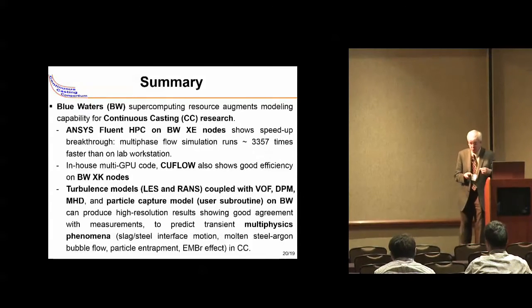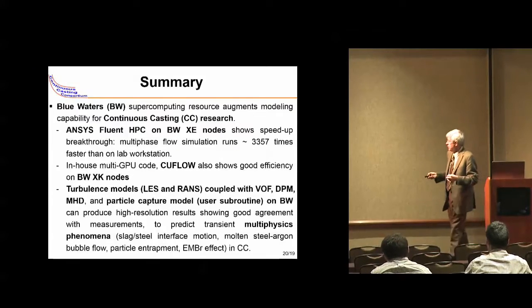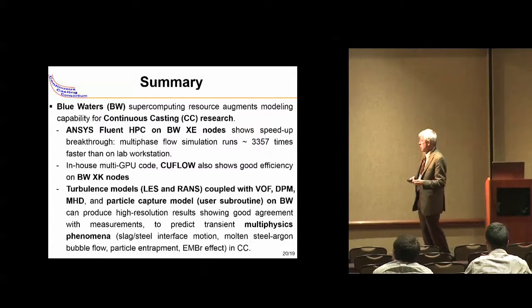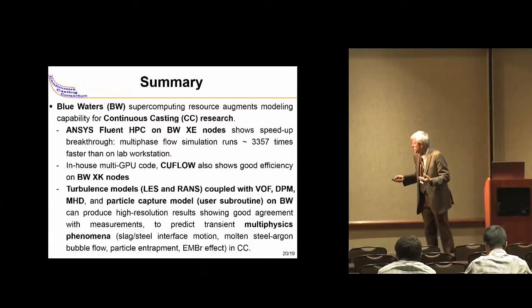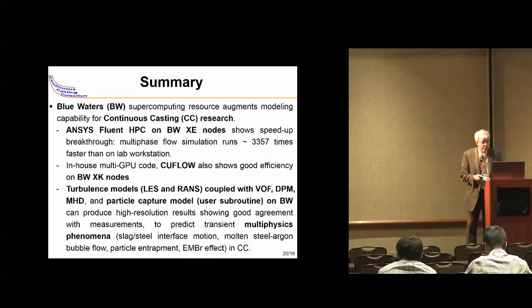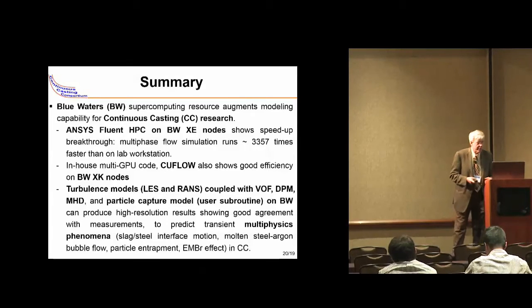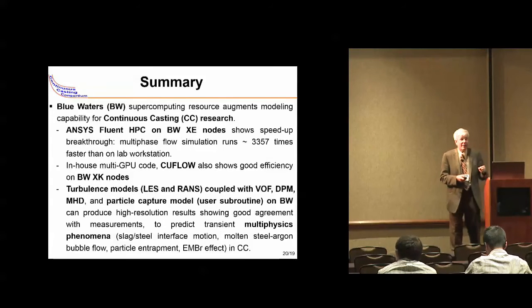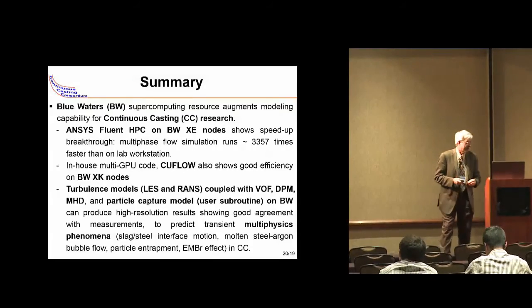Finally, if we take good high fidelity models—large eddy simulation coupled with the volume fluid method, the DPM, MHD—we can actually get high resolution predictions that show good agreement with measurements in the real plant. Then we can predict these multi-physics phenomena such as interface motion, the movement of bubbles, the entrapment of particles, and most importantly we can do it fast enough to actually do parametric studies to make practical improvements to the plant.